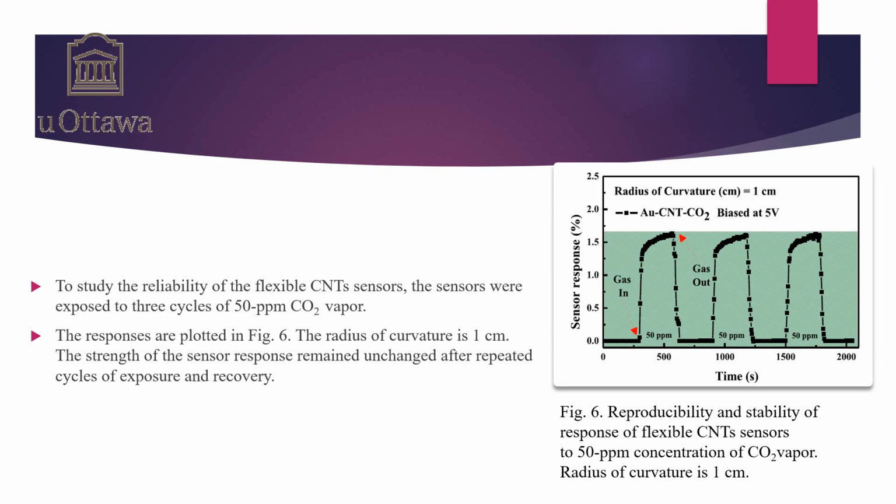The strength of the sensor response remained unchanged after repeated cycles of exposure and recovery. Notably, the sensor response was good in the tested bending state. These results reveal the potential of the developed flexible sensor to be reliably operated even in passive recovery mode with an acceptable loss of sensitivity, making them suitable for low cost and low energy applications.